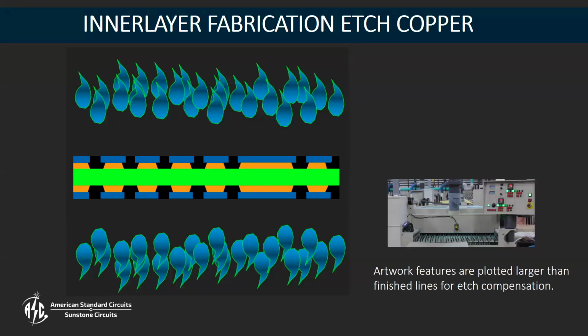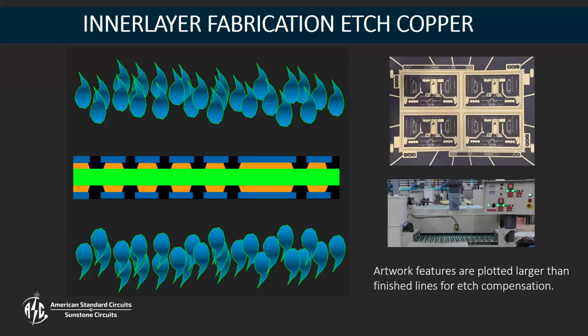There are some things with chemistry and temperature that can help mitigate that a little bit, but in general, you're going to get kind of a trapezoidal shape to your traces, usually less pronounced on inner layers than outer layers. Okay. There's an example of a panel with the copper etched away now. That is kind of a higher speed material, so it's kind of a white colored laminate as opposed to a yellow for FR4. But that's what you're seeing there, the laminate and the photoresist.